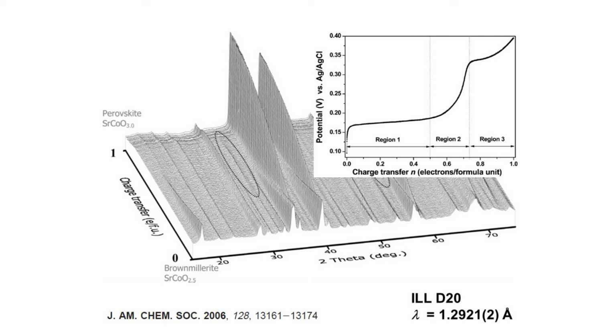So this is the evolution of the potential during the experiment, and we see that basically we have three regions. The first region is up to a charge transfer of 0.5 electrons. This means that we reach the intermediate stoichiometry for oxygen, 2.75, which is exactly in the middle of this transition. We have in first approximation no change of potential. This means that we are dealing with a biphasic system, and we have always the same phases.